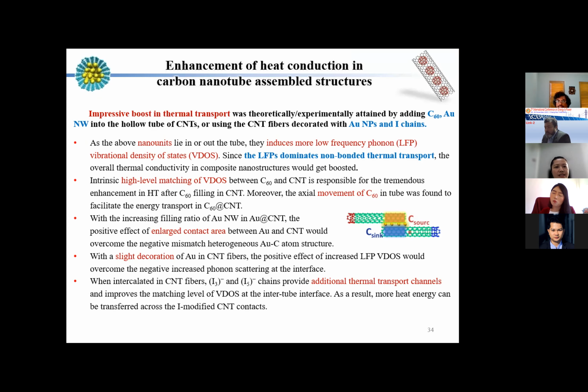For enhancement of heat conduction in carbon nanotube assembled structures, we get it by adding carbon-60 or gold nano-units into the hollow tube of CNTs, or using fiber decorated with gold nano units lying in or out the tube. They introduce more low frequency phonon, LFP, vibration density of states, since LFP dominates non-bonded thermal transport. So the overall thermal conductivity in composite nanostructures would get boosted.